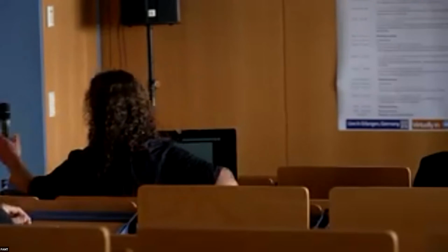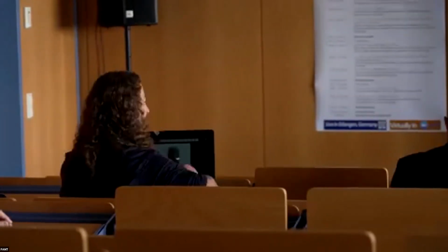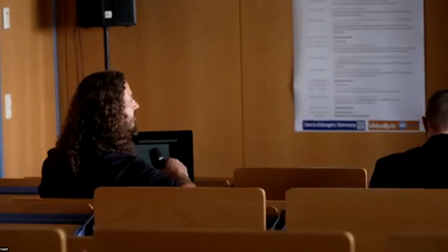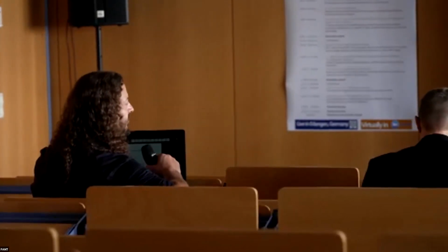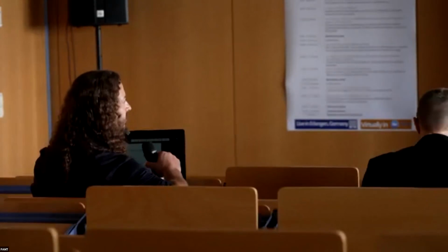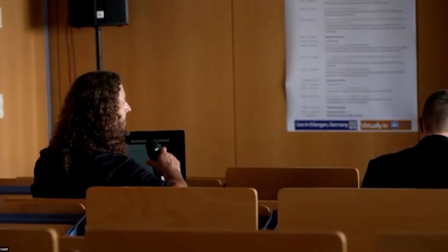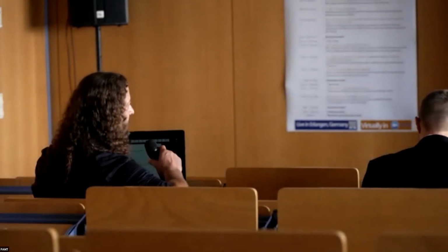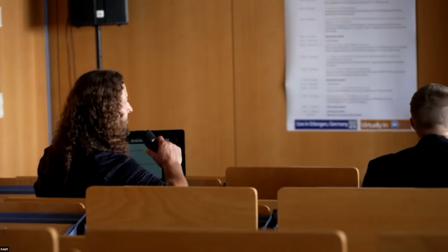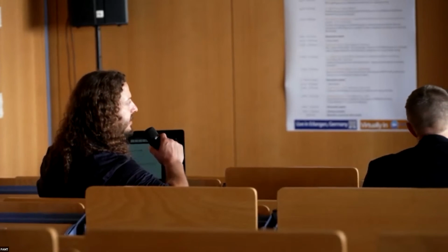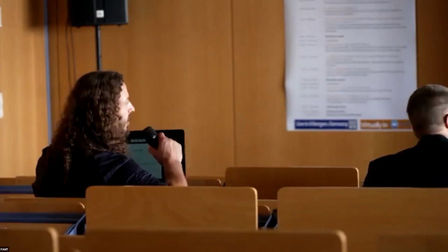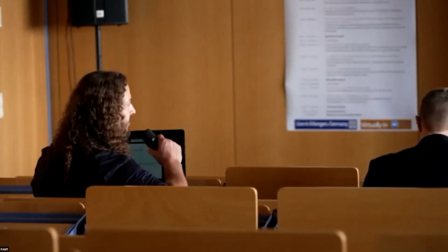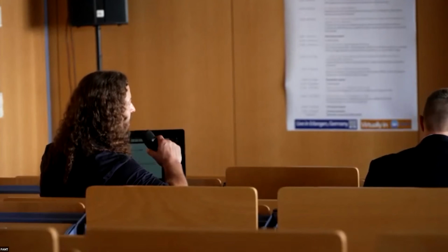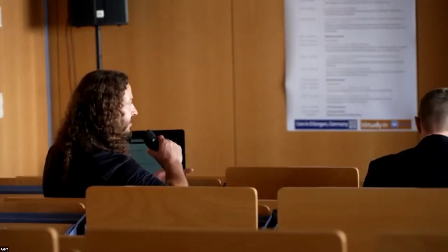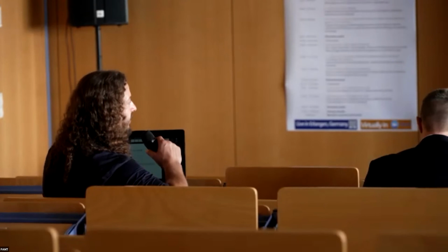Thank you. Alex, I actually have a follow-up question for you, because you mentioned that you did the measurements in the high vac, obviously to try to get rid of the influence of any humidity. Did you also bake the sample while it was inside the high vac to eliminate any of the moisture or not? For this kind of sample, we did not bake at elevated temperatures. We simply let it rest over a longer period of time while vacuuming the chamber and establishing really stable content. However, we can, of course, introduce the heating station within the high vac and then anneal the samples. But for this experiment, we didn't.